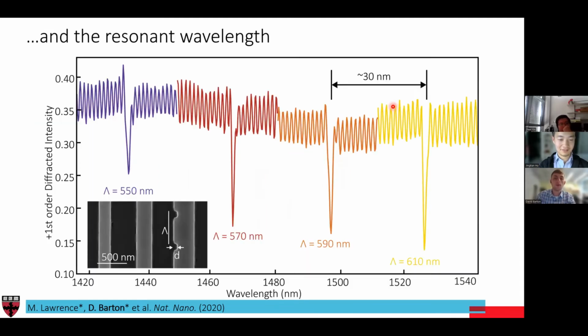And we can also go further, and we can dynamically or deterministically decide where these resonances actually occur. And so if we change the period of the structure, we can actually place exactly in frequency space where we want this to occur. And so here, by changing the period by about 20 nanometers, we can actually change where the resonance appears by shifting it around. And so what this really showed for the first time is that you can design these individual nano antennas in these metasurfaces to design ultra high quality factor devices.